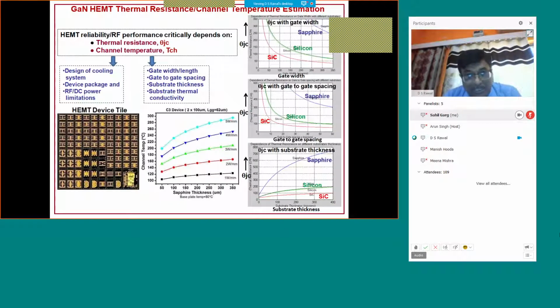And similarly, since very high current densities are involved, a lot of heat is generated. So we have to control the channel temperature of these devices also. And again, that channel temperature is a function of gate width, gate length, substrate thickness, and substrate thermal conductivity. And this channel temperature governs the design of your cooling system or the package which you are going to use once these devices are used in the actual systems.